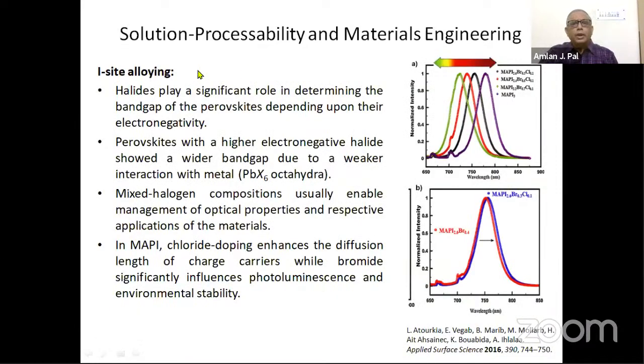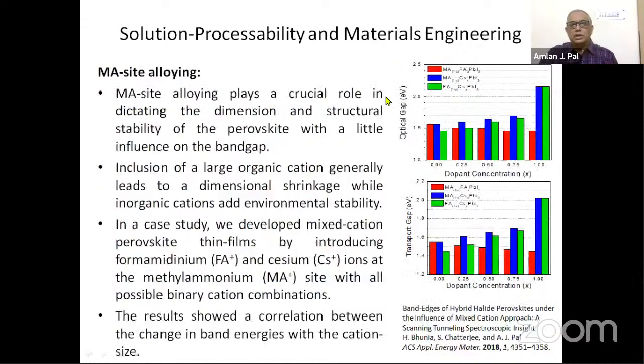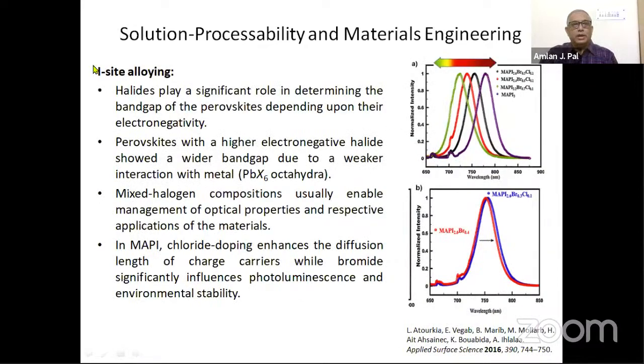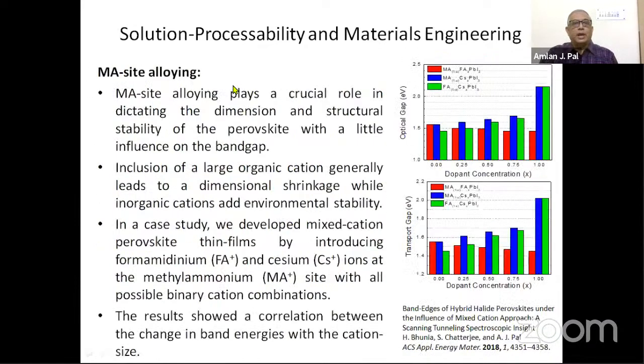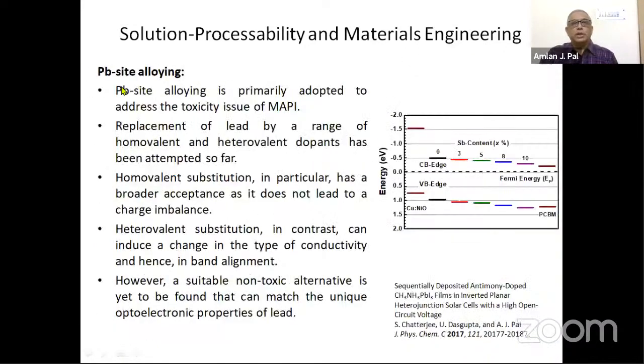And I said about this materials engineering, you change the iodine side, or the methyl ammonium side, or the lead side. By doing this kind of solution materials engineering, you can vary the band gap. As you can see here, the normalized absorption plot, the normalized PL here, and absorption, you can vary the band gap of the material by simple solution processing and materials engineering. I have just given some examples of alloying at the iodine side, at the methyl ammonium side, and also at the lead side.